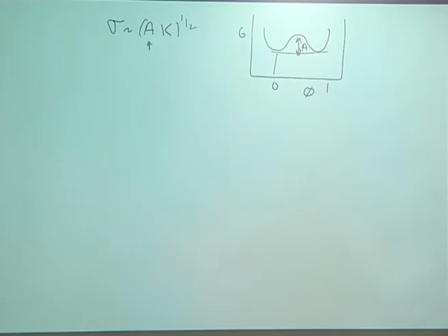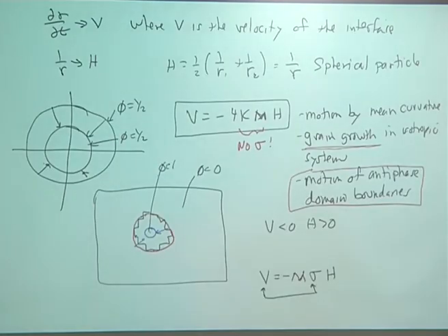As you get towards a critical point, in this case a tricritical point, this amplitude A goes to 0. And so you basically have a handle on the interfacial energy. All you have to do is change the temperature in your experiment, and that's precisely what they did. They changed the temperature by a lot towards the critical point, changed the interfacial energy by an order of magnitude, and the evolution process didn't change. The rate didn't change. So it was independent of the interfacial energy. Of course this is pretty controversial, but he was right.